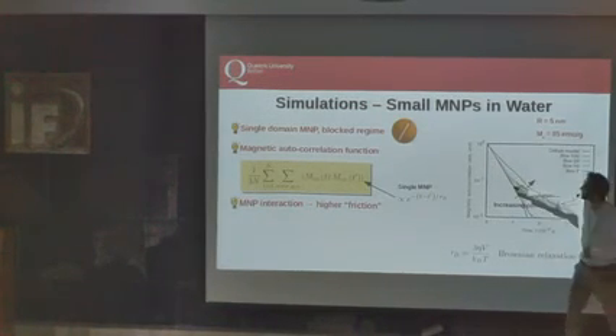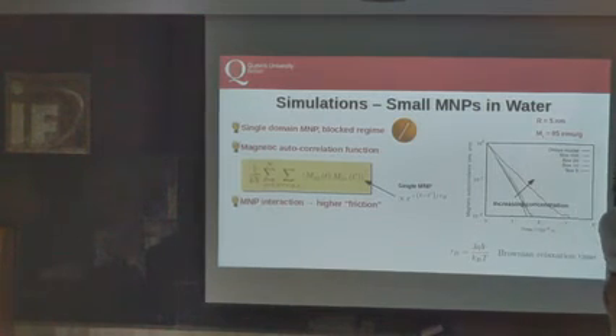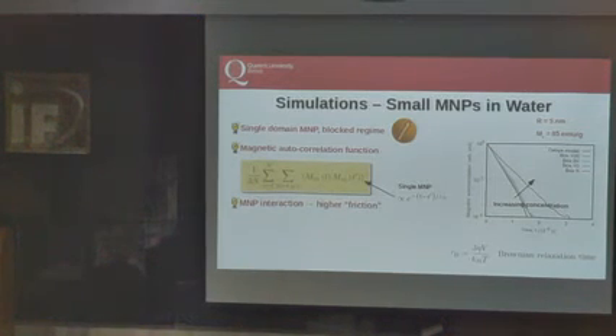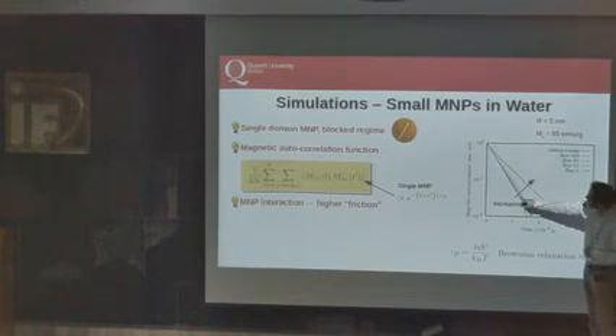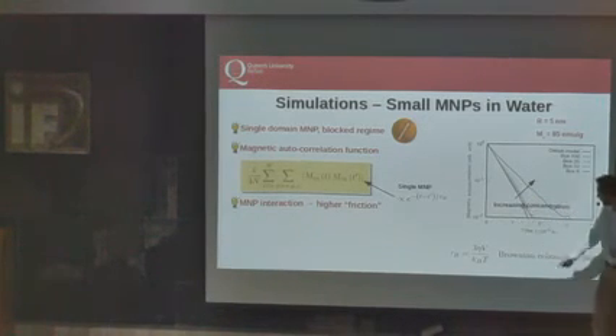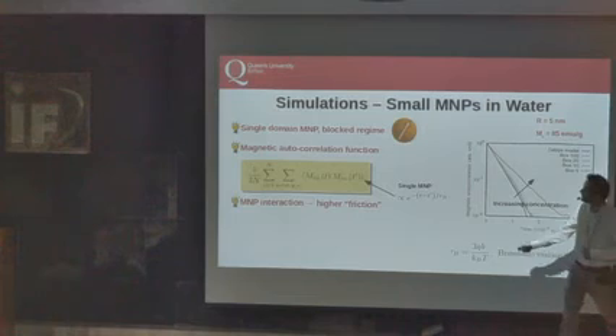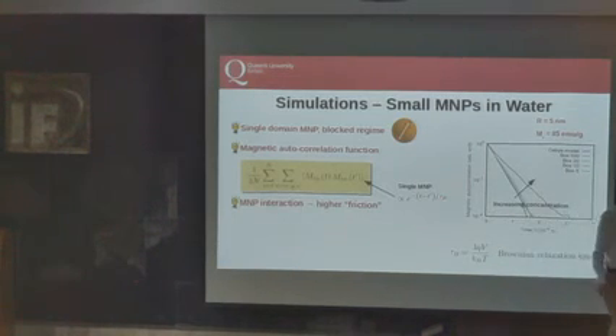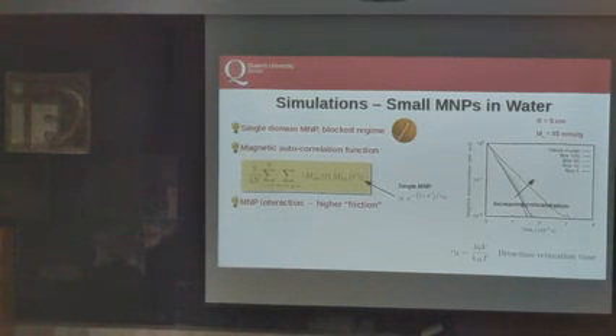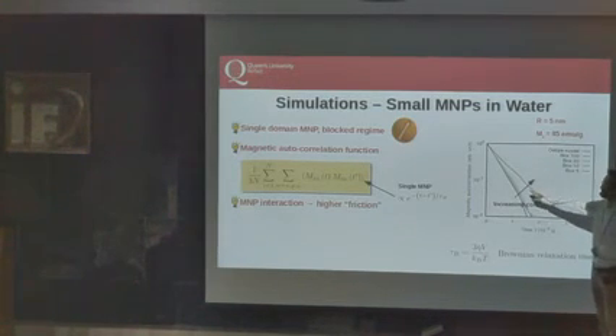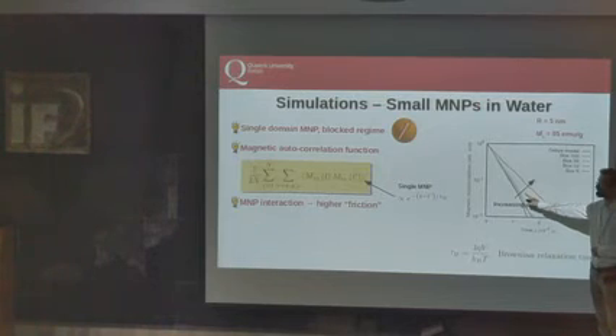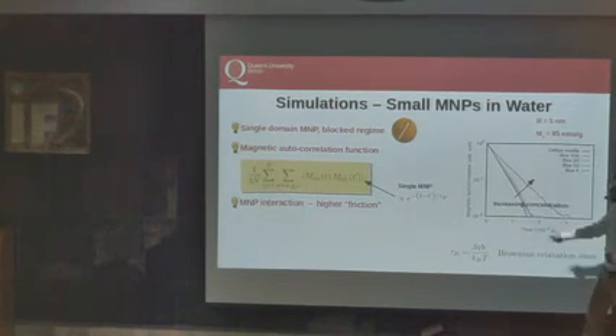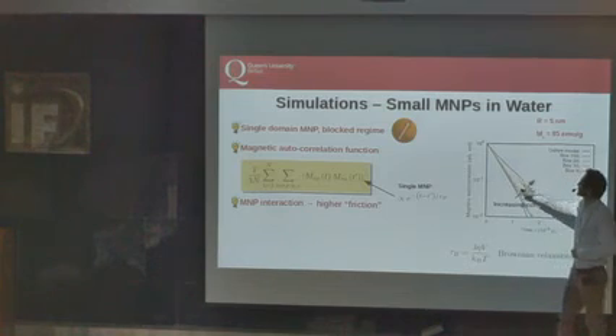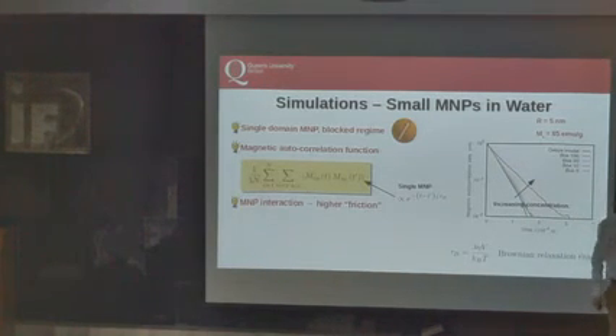This box 5 means that it's almost all coagulated. At low concentrations, there is almost no difference from the single particle results. So the effect of aggregation, the effect of many body interaction is not very high. But if we increase the density, increase the concentration, we have strong deviation. We can still describe this as a decaying exponential.